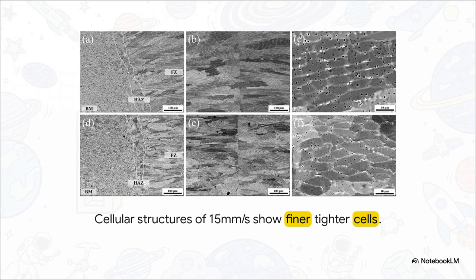Now, let's zoom in even further. I'm talking right down to the cellular level, inside the weld itself. Because as the weld cools down, the metal crystallizes into these cellular columnar structures. The image on the left is our 15 millimeter per second weld, and the right is the 20 millimeter per second weld. You can visibly see it, right? The 15 millimeter per second weld on the left created significantly finer, smaller cellular substructures. The thermodynamics happening here are just fascinating.